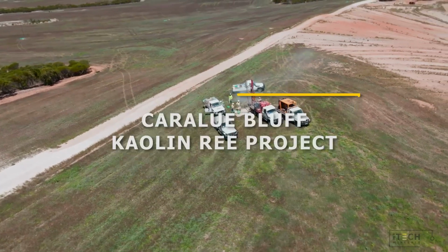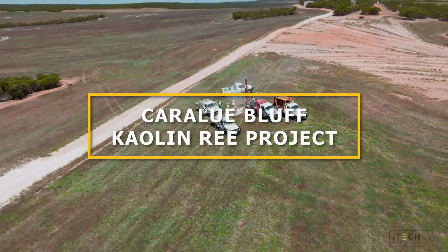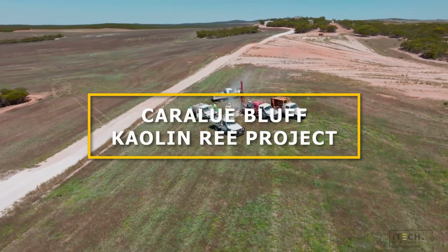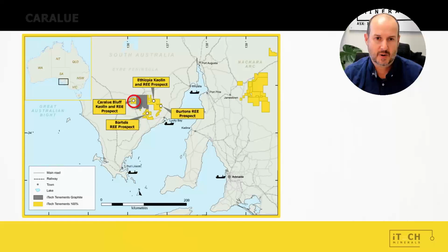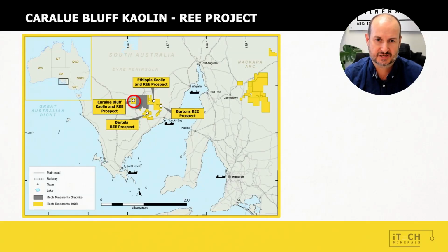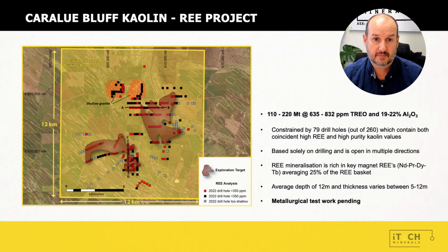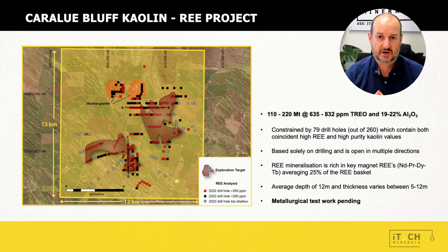So moving on to our CARALUE BLUFF Rare Earth and KAOLIN project, significant drilling has been done over the last year on this project, where we've proven up a significant exploration target of both KAOLIN and coincident rare earths at CARALUE BLUFF. We completed approximately 260 drill holes on this prospect, of which 79 have been incorporated into an exploration target. Now, we've kept that exploration target to include the high purity kaolin and the coincident rare earths.